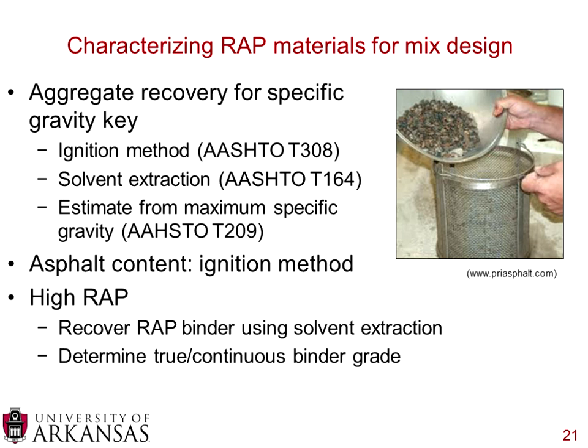They recommend that if you are just looking for the asphalt content, use the ignition method. That's the easiest, fastest, and most consistent method. And if you are using high RAP, you want to recover your RAP binder using your solvent extraction technique so you can determine the true or the continuous binder grade of the RAP material.